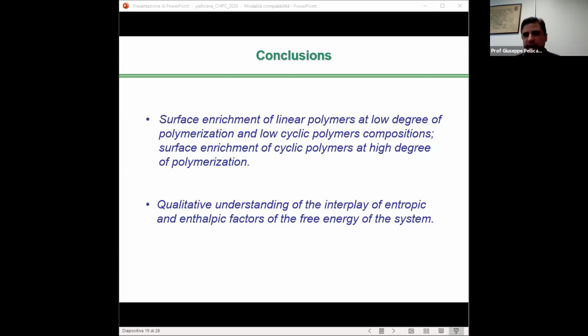In a similar way, linear polymers at the interface become favored because they have a smaller energy per bead. So in this scenario, the linear enhancement that we observe at the interface in the case of short chains is the result of an entropy-mediated process, where energy also plays an important role.